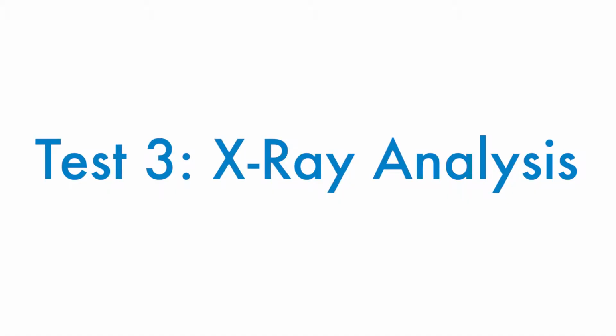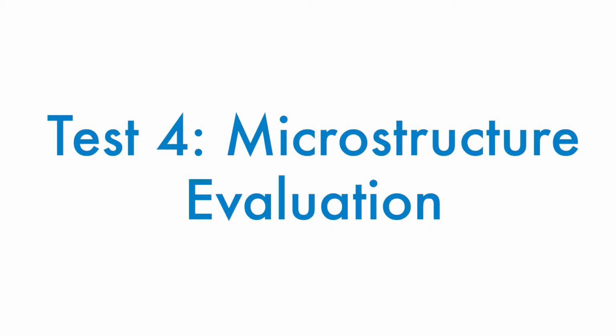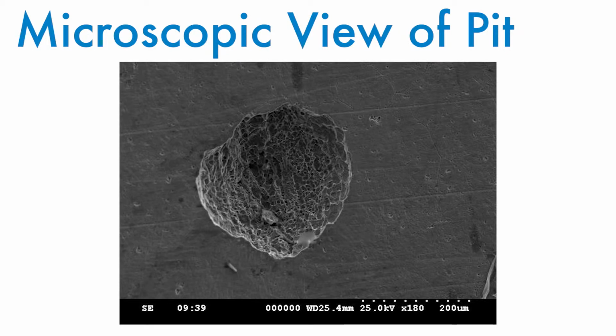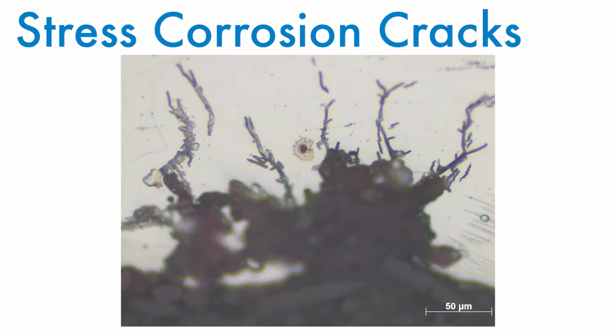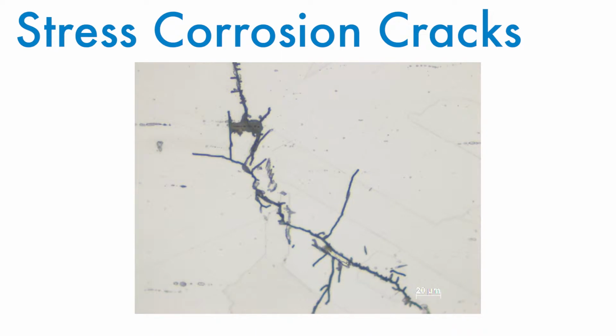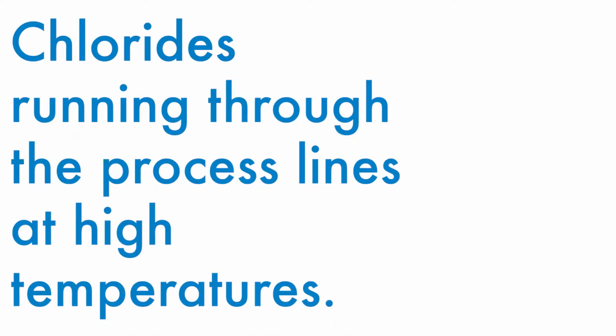An X-ray analysis also identified the presence of a well-known pitting and cracking agent to 300 series stainless steels, chloride. Lastly, microstructure evaluation exposed flaws that can be introduced during fabrication, welding, heat treating, and even coating. Corrosion pits were also present, and stress corrosion cracks from the welds were found to be caused by cold weld stresses during fabrication. With the results from the 4 tests, CSI confirmed that the pitting and cracking was caused by chlorides running through the process lines at high temperatures.